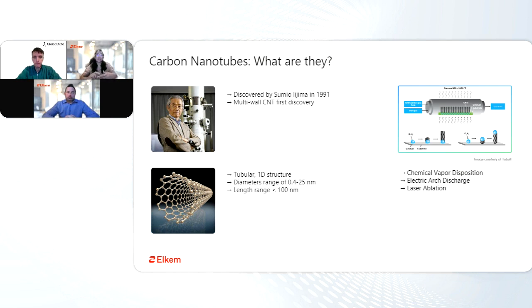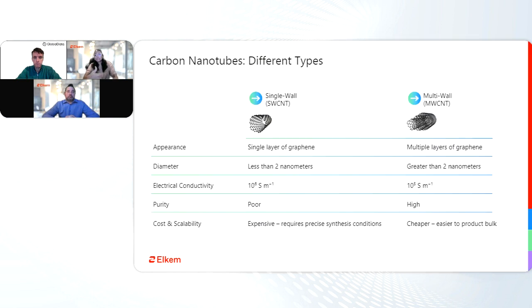These tubes are one-dimensional structures with diameters ranging from 0.4 to 25 nanometers and lengths that vary, but are shorter than 100 nanometers. Typical methods of synthesizing them are through CVD, chemical vapor deposition, electric arc discharge, and laser ablation. With these methods, there are two different categories of carbon nanotubes that you can create. I'd like to touch upon the single and multi-wall carbon nanotubes.